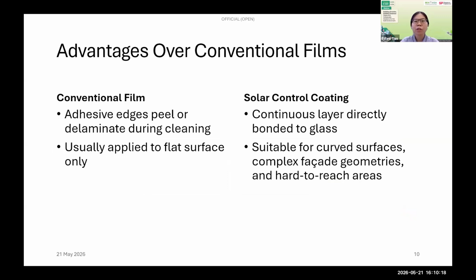So you may wonder how this compares to conventional solar films. The key difference comes down to how the coating bonds to the glass. Conventional films rely on adhesive, which tends to peel or delaminate over time along the edges, especially when moisture gets in during routine window cleaning. So our coating forms a continuous layer bonded to the glass surface, eliminating those failure points and reducing maintenance requirements.